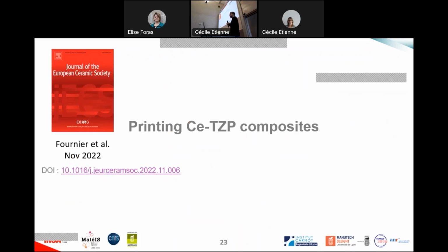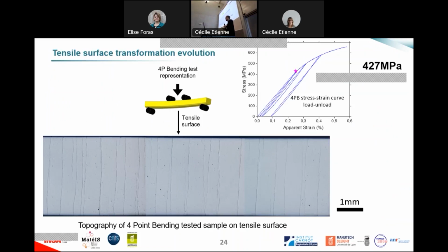So now, focusing more on the mechanical part, I'm going to show you results on ceria-based zirconia composites. So it's a different zirconia. And why do we use this type of zirconia? Before this work, during 40 years, there has been development of this doping of the zirconia to permit it to transform. So when you have a sufficient mechanical stress, you have a local transformation to permit a bigger change of the geometry of the sample, and to have a type of plasticity that we can't achieve with the other ceramics.